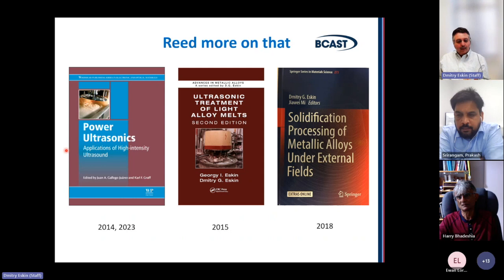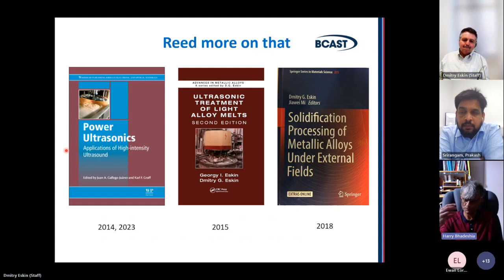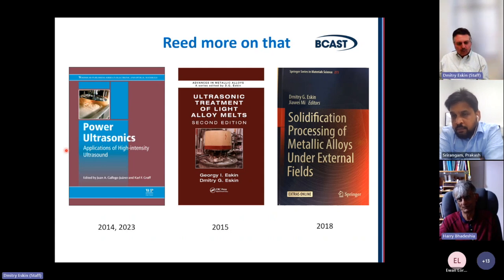It may work. You can also achieve some effects similar to degassing by introducing vibrations, and that's of course easier, depending. For shape casting, it's quite easy. You can just put your mold on the vibro table. The big advantage of doing that would not be grain refinement because the steel is processed afterwards anyway. It would be reducing the scale of chemical segregation. You can probably reduce the level of macrosegregation by reorganizing the flows, and also you can achieve some degassing, some better mixing of liquid and semi-liquid material. But this is a different area of research.